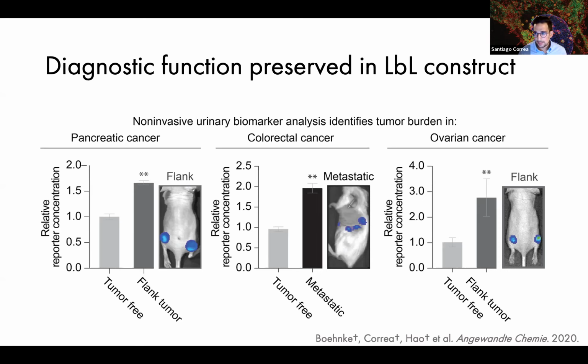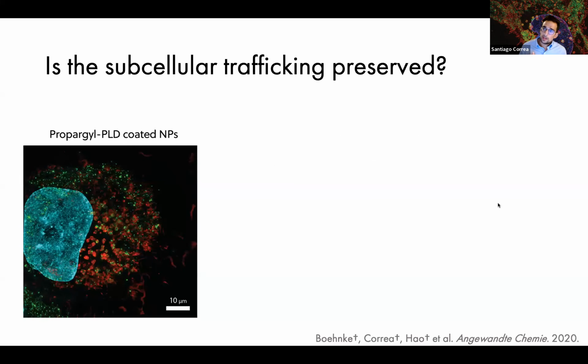And what we wanted to see next is if all this tinkering with the surface chemistry of the LBL nanoparticle may have changed the subcellular trafficking profile that we were trying to work with. So as you recall, the original polyaspartic acid system was localized on the interior and on the exterior of cells. And we looked at our propargyl modified system, so this is before doing any further click addition. We see a really similar subcellular localization of these nanoparticles. So this green signal that we see arcing around the cell here in this micrograph are surface localized nanoparticles. And then we see nanoparticles localized into these vesicles as well, indicating that we are still gaining entry into the cell.